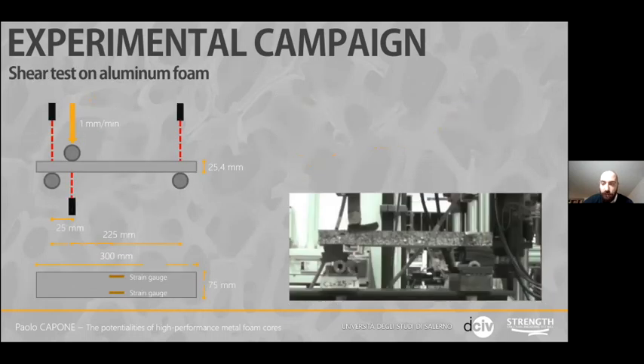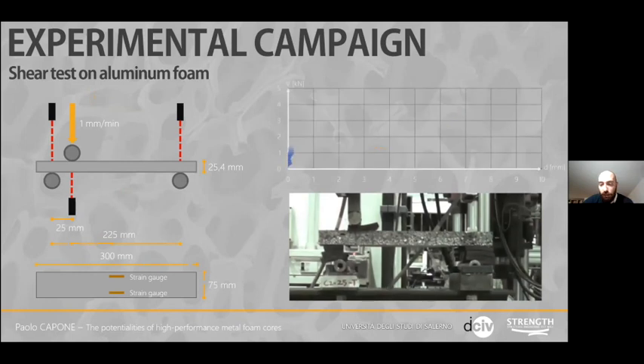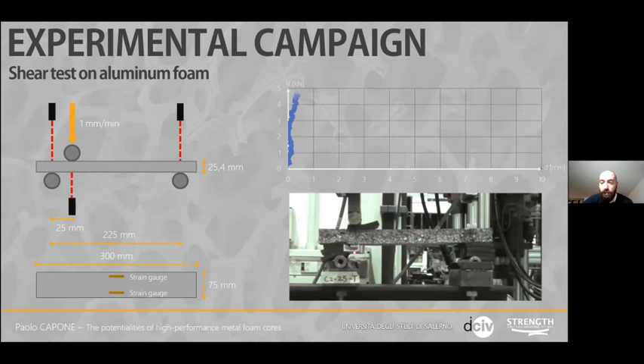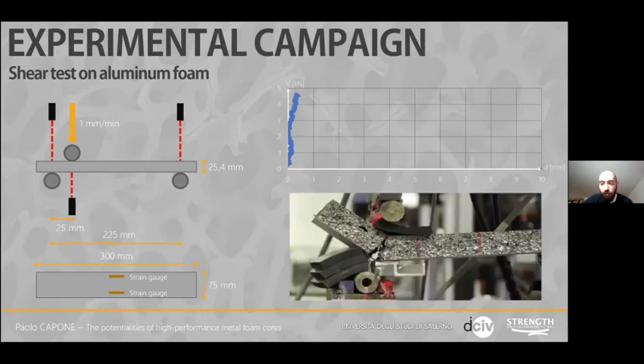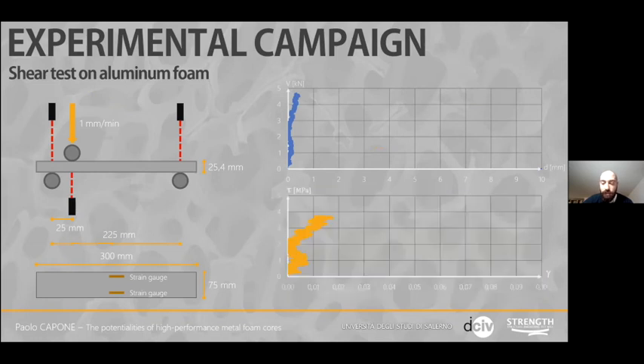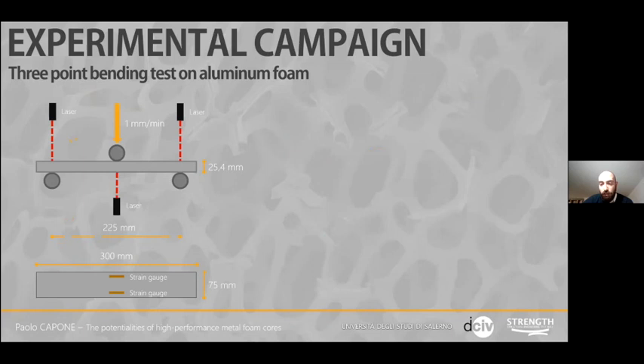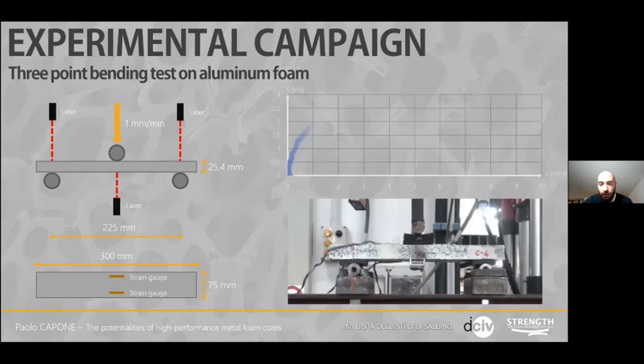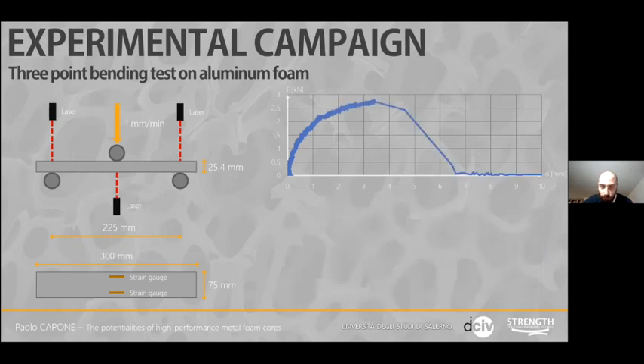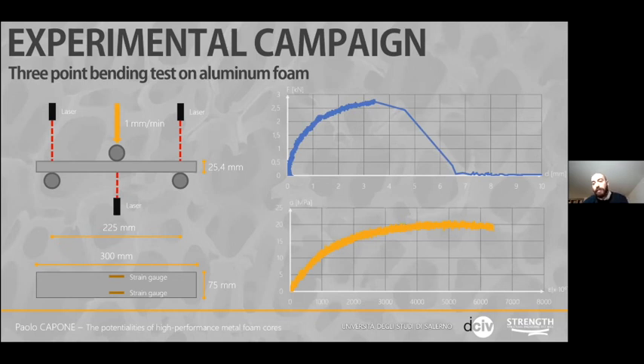The second step of the experimental activity has regarded the shear and bending tests only on the aluminum foam. 3-point bending tests and shear tests have been executed varying the point of application of the force. To assess the displacement of the specimen, three laser transducers have been installed, and two strain gauges for each side. And these are the results of the 3-point bending test on the aluminum foam. The results of the test can be visualized on the diagrams, and they show a yield point of about 20 megapascals and a bending modulus of about 10,000 megapascals.